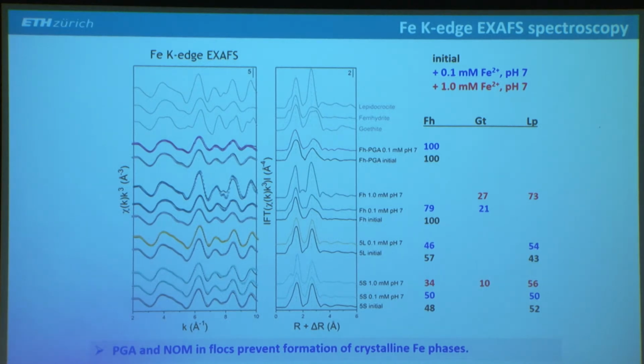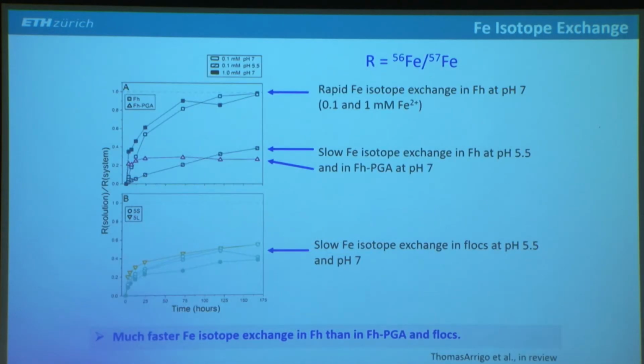So this suggests that the natural organic matter actually inhibits a recrystallization of the polycrystalline iron phases, but it doesn't tell us anything about possible atom exchange. It could still exchange, but you might form new ferrihydrite in the presence of organic matter. So it's important to also look at the isotopes, and if we do that, we find the following results.